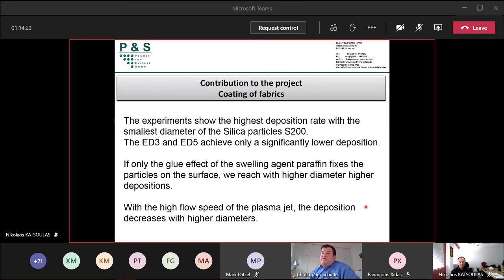With the high flow speed of the plasma jet, the deposition decreases with higher diameters. That is what I mentioned before. So the S200 quality with 3 micron diameter was the best quality of silica. So going on with the project, we always concentrate on this S200 quality. Okay, the next page, please.